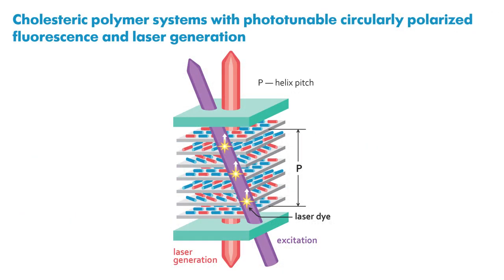Using the same principle of the helix photocontrol, we have realized cholesteric polymer systems with phototunable circularly polarized fluorescence and laser generation. Introduction of fluorescent or laser dye molecules into the cholesteric matrix allows one to obtain circularly polarized emission or lasing from such films under light excitation.